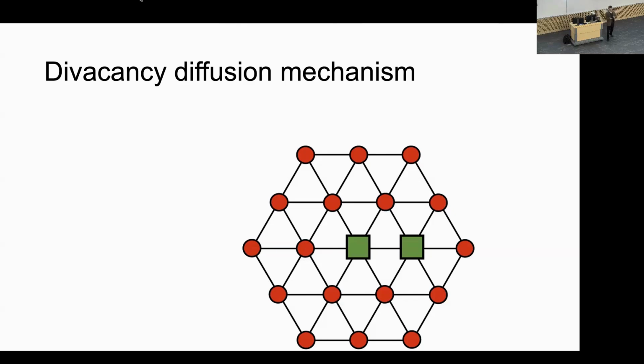Well, if you take a crystal and you try to mechanically deform it, you can't glide the whole layer because the energy scales with the whole area, right? So it's kind of like moving the rug through the little dimple in the rug, right? Yeah. Like we all learn in the beginning in material science. So it's the exact same arguments. So in these materials, the layer won't glide instantaneously. It has to be kind of a phase front that moves, but the interface is really a partial dislocation. That's the hypothesis, and we need experimentalists to see it.